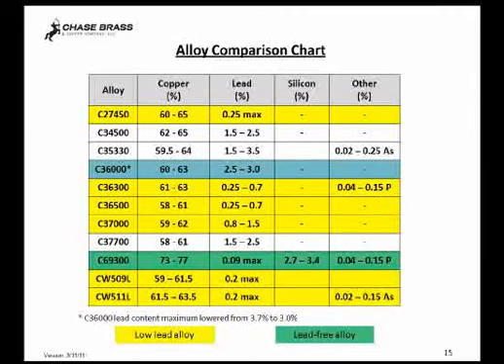And alloy 360 always contains 60 to 63% copper, 2.5 to 3.0% lead. But in October of 2010, the ASTM standard was changed to drop the maximum lead content from 3.7 to 3.0 so that alloy 360 could be used by some component manufacturers in their drinking water contact parts.